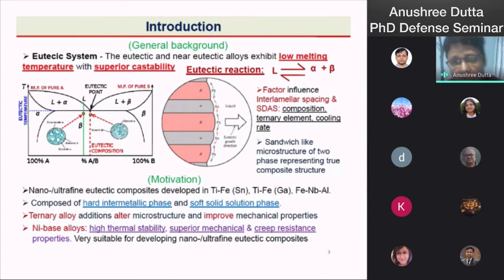We know eutectic and near-eutectic alloys exhibit low melting temperature with superior castability. In a eutectic reaction, liquid is transformed into two solid phases. In a eutectic phase diagram, the lowest melting point is the eutectic point, where the entire microstructure is eutectic with two phases. In pro-eutectic compositions, some portion of pro-eutectic phase is present along with the eutectic microstructure, which changes the mechanical and other properties of the alloy. Several parameters influence these properties, such as interlamellar spacing and secondary dendritic arm spacing, which are controlled by composition, ternary alloying element and cooling rate.